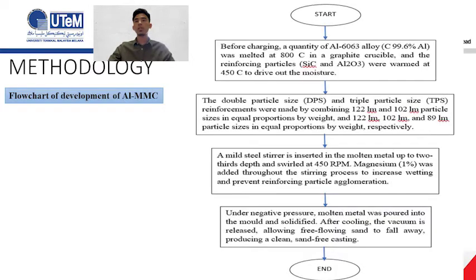The next is the development of the aluminum metal matrix composite. Before charging the quantity, aluminium 6063 alloy, for example, was melted at 800 Celsius in the graphite crucible and the reinforcing particles. And then the double particle size and triple particle size reinforcements were made by combining. And then a mild steel stirrer is inserted in the molten metal up to 2/3 deep and stirred at 450 rpm.